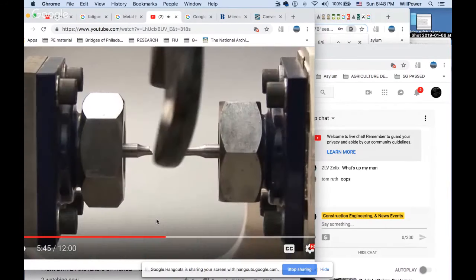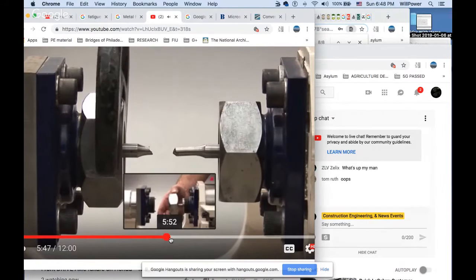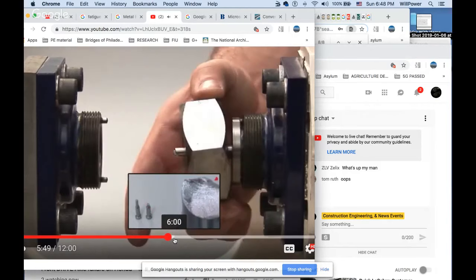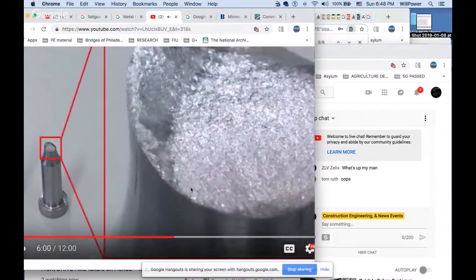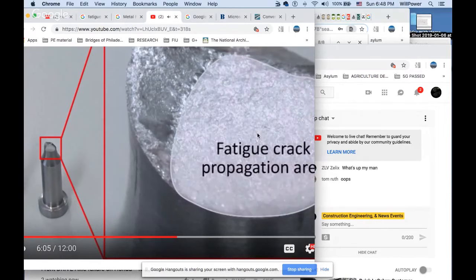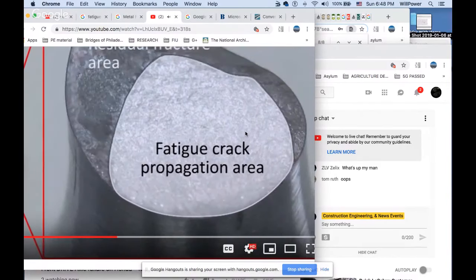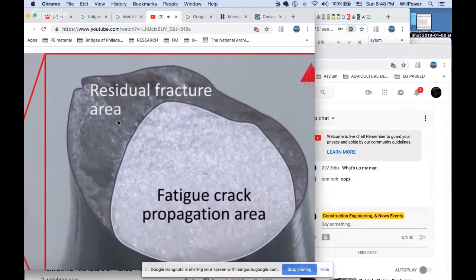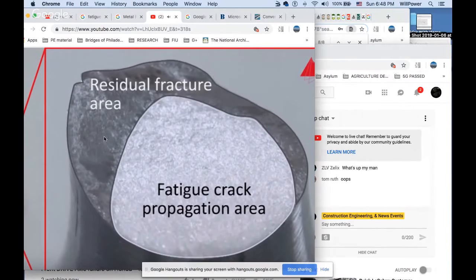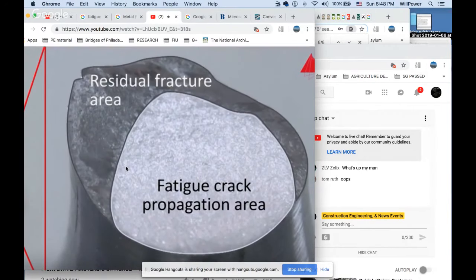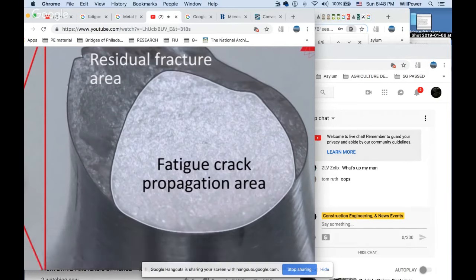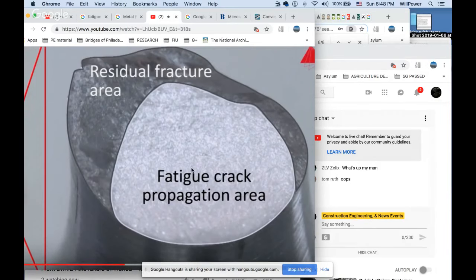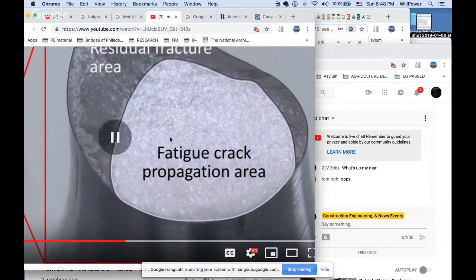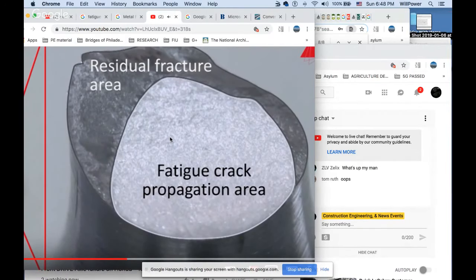The first test is finished. The material tester removes the fragments cautiously and inspects the fractures. It reveals two regions: the rather dull, predominantly flat fatigue crack propagation area and the rough residual fracture area. The residual fracture area results from the final catastrophic rupture. The fatigue crack propagation area has developed during the cyclic growth of the fatigue cracks, starting at the surface of the specimen.